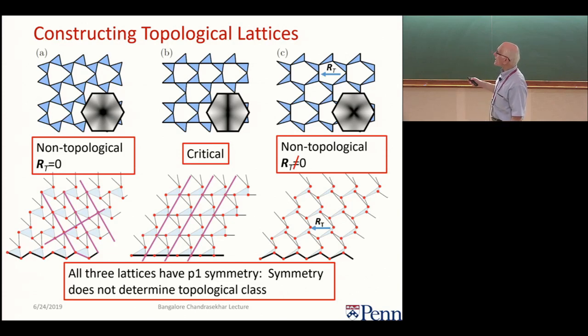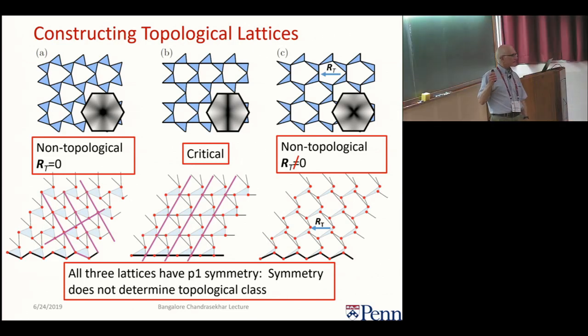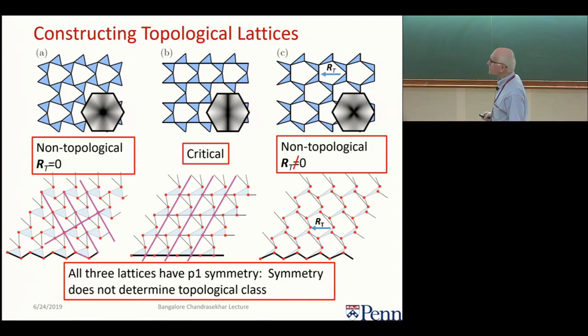And this one, you can notice, is really polar. It has no inversion symmetry. It's polar, which means there is a possibility of defining a vector associated with it that defines a direction in the lattice. Here it looks like we have 0 modes, but that is also another thing that comes out of the predictions of this theory. These are modes whose frequency goes as wave number squared instead of just the wave number, which is what happens for phonons. So it looks like they're 0, but they go up.